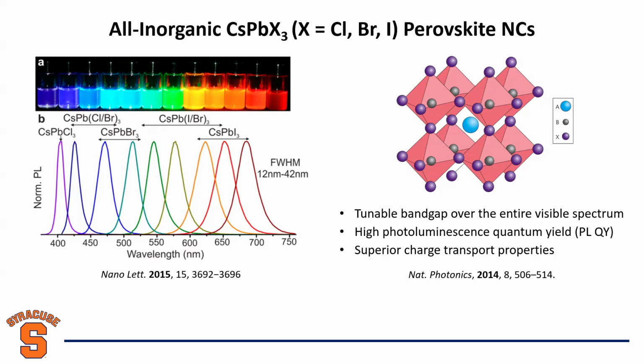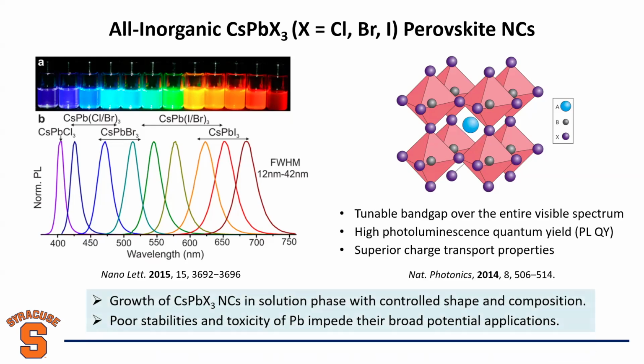Okay, so this is the structure of the metal halide perovskite materials. The B-site sits in the center of the octahedron formed by six halide ions, and the cesium sits in the big hole between eight octahedra. You can see it's a cubic structure, right? So, excellent properties. You can see many good papers related to perovskites every day. But there are two problems related to perovskites fundamentally. The first one is, as I said, the cubic phase: how can we do shape control? And the second problem is the very limited stability of perovskite materials due to their ionic nature.